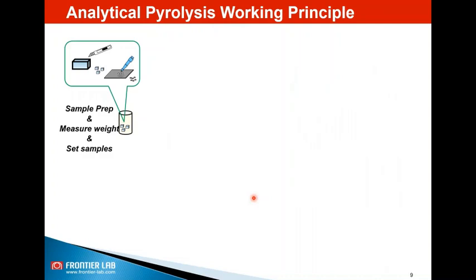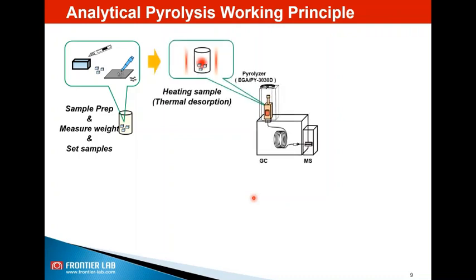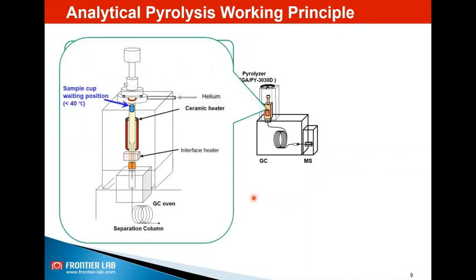As I said, you don't need any sample preparation. That means you can transfer a representative sample, using an appropriate sampling tool, to a sample cup. Then this sample cup will be dropped into the micro furnace where the temperature is set for a certain type of analysis. Within the furnace, you have a sample waiting position which is less than 40 degrees, so the sample is exposed to high temperature only when the analysis starts. When you start the analysis, the cup drops into the hot zone, the heating zone, where it is exposed to high temperature, because of which the additives and also the monomers of polymers are released from the material.